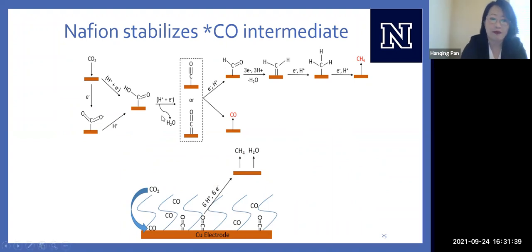What do I mean by that? So when we do CO2 reduction reactions, one intermediate that happens is a CO intermediate in either one of these two configurations. At this stage, CO can pop off and we can detect CO as a product. So that's one thing that could happen. But if the CO intermediate remains on our electrode surface, it can continue to take on some electrons and protons to protonate and make methane.